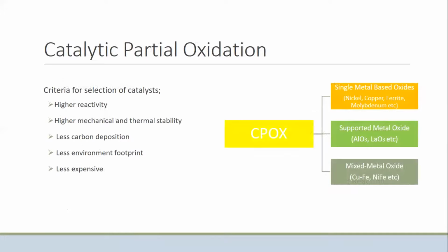Many catalysts have been investigated for the partial oxidation reactions, such as expensive noble metals, non-noble metals, mixed oxides, and supported or unsupported catalysts. Other than the high performances of the noble metals, nickel stands out for its high efficiency. But carbon formation on nickel catalyst decreased the stability of the reaction. To support that, aluminum and lanthanum were investigated with nickel along with other metal oxides. Considering all of this, there are some criteria for the selection of catalyst. It must have higher reactivity with high mechanical and thermal stability, less carbon deposition, and be less expensive.